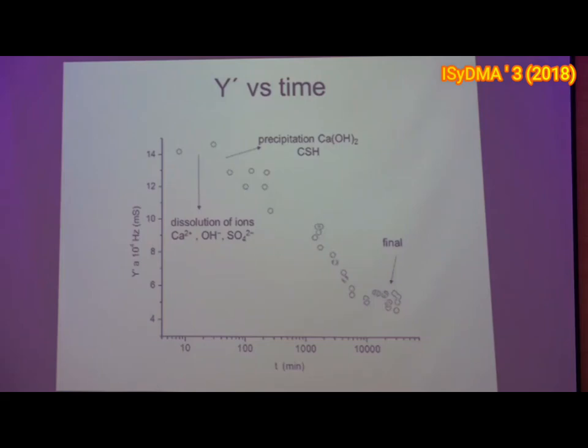So here, for example, we see the evolution of the admittance real part as a function of time. This is about 1 month. In the beginning it increases a little bit. This is due to the dissolution of ions. Then precipitation decreases it. This is several days. And then this is practically constant. That means that the cement is completely cured and we have a good material.